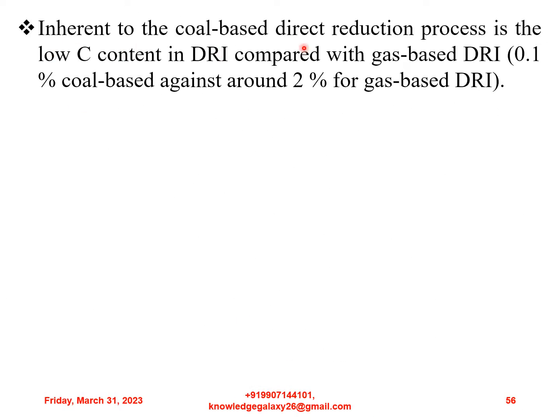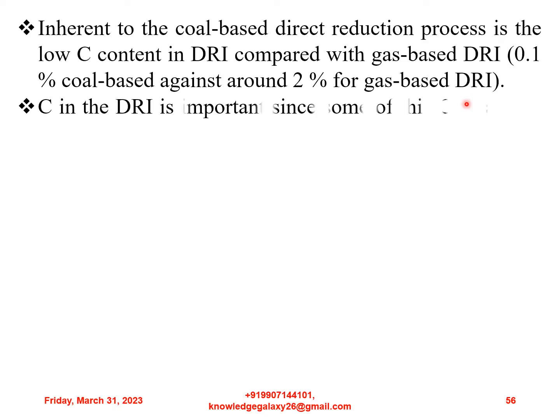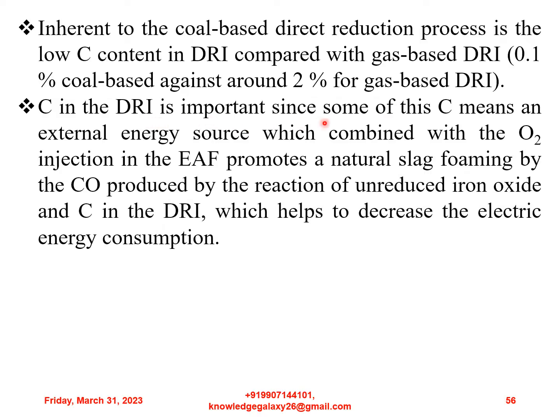Inherent to the coal-based direct reduction process is the low carbon content in DRI compared with gas-based DRI: 0.1% for coal-based against around 2% for gas-based DRI. Carbon in the DRI is important since some of this carbon means an external energy source which, combined with oxygen injection in the electric arc furnace, promotes natural slag foaming by the CO produced by the reaction of unreduced iron oxide and carbon in the DRI, which helps to decrease the electric energy consumption.